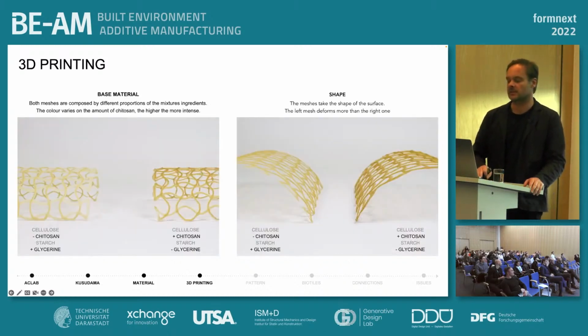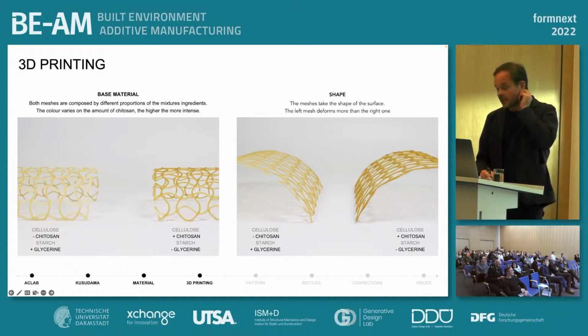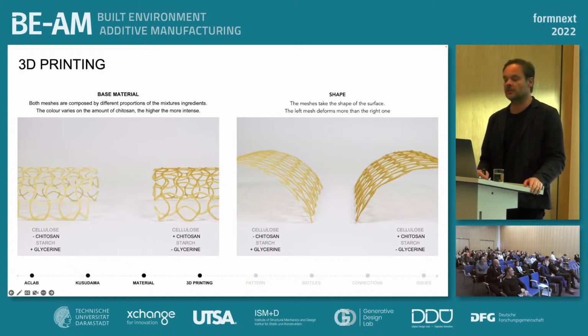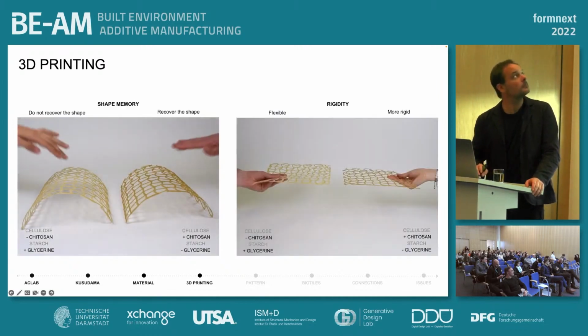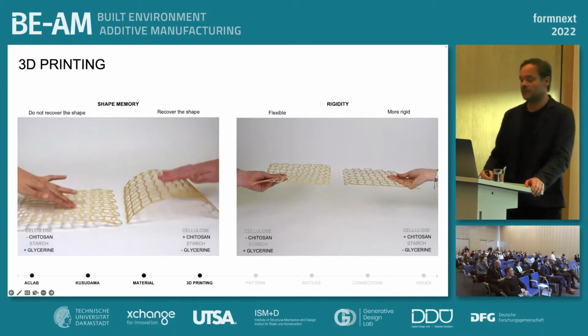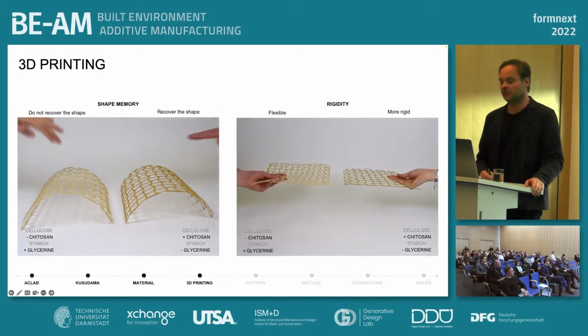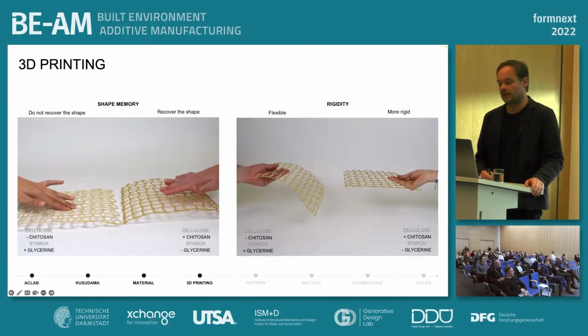A second set of tests was done. Here we show 2 grids. Here we were printing 4 layers for each one of those specimens, and we were using again different amounts of chitosan and glycerin. And it's possible to understand that the more chitosan, the more rigid and dark the material gets. And also, we see that on the left grid, a higher percentage of glycerin has a better plastic behavior.